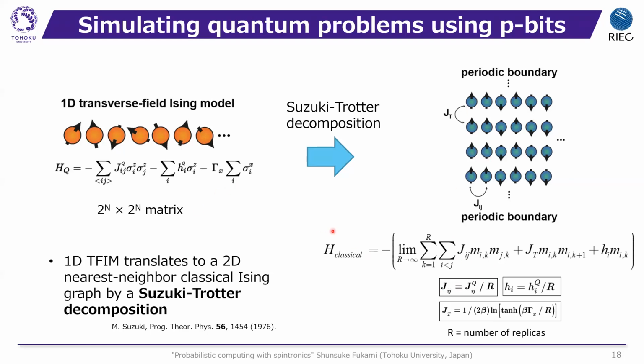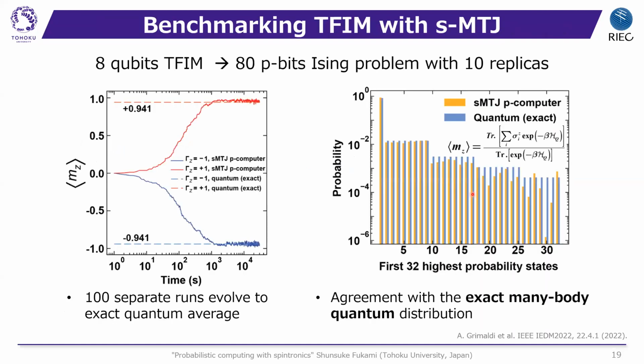using these equations. So the one-dimensional transverse field Ising model translates to the two-dimensional nearest neighbor classical Ising graph by using the Suzuki-Trotter decomposition. So using this scheme, we simulated a one-dimensional transverse field Ising model using our probabilistic computers. Okay, so let me show the results. In this experiment, we applied the annealing scheme to find the solution of the quantum problems. So we observed the convergence of the systems to a particular state.